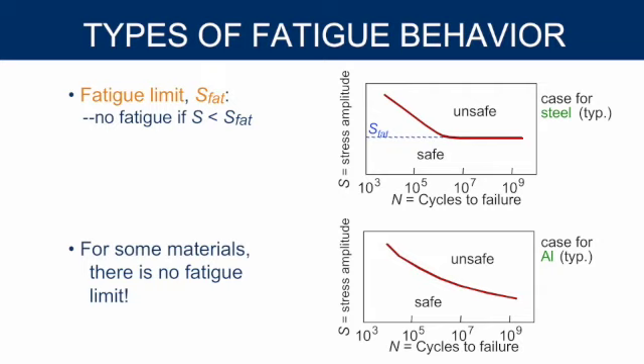All right, so we ended the class with the fact that fatigue can cause a material to fail well below its actual yield strength. This is due to the fact that as you cycle it over many cycles, the cracks and the voids in the material start to expand due to the pressures being released and added again over and over again, and the material will eventually fail. Some materials, though, do have an endurance limit where anything below that limit will not fail as long as the stress is below that. But if the stress is high enough and it hits the line, that results in a failure. Okay, so things like certain types of steel basically will blunt out a lot of the voids so that they will almost have a self-repairing type of result.